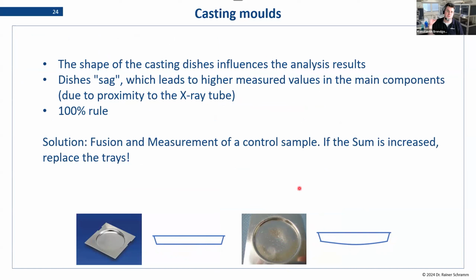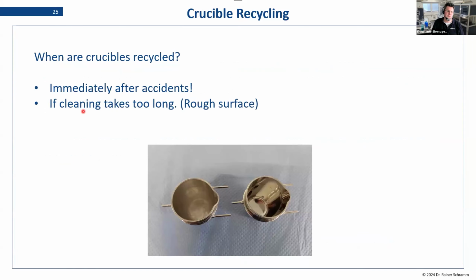analysis. Usually what you find is that the sum of analytes in your sample is more than 100%, and you can usually see an increase in the main components. So that's a clear sign that your dishes need to be replaced, and you can actually use this effect with a control sample that you run regularly, and then you can see when it's time to replace your casting molds.